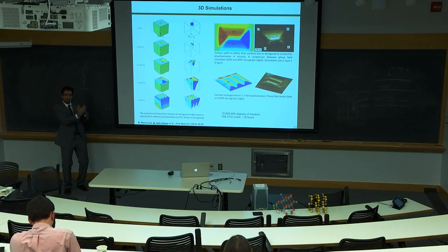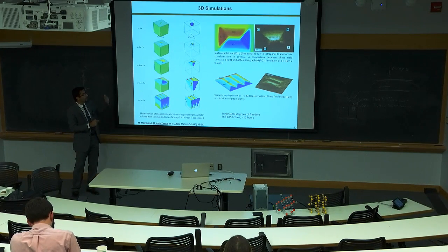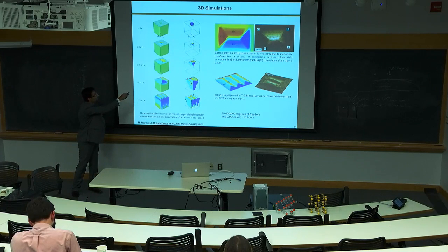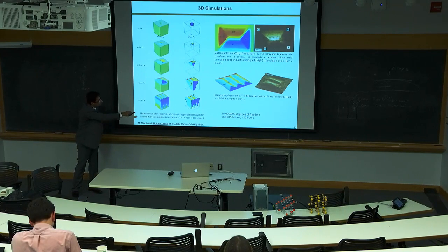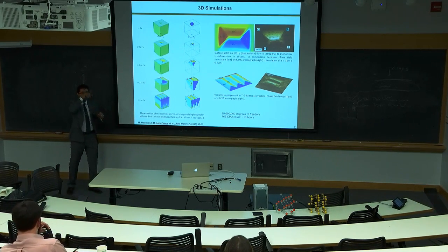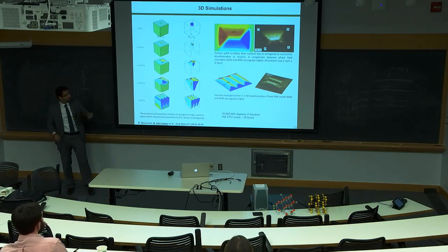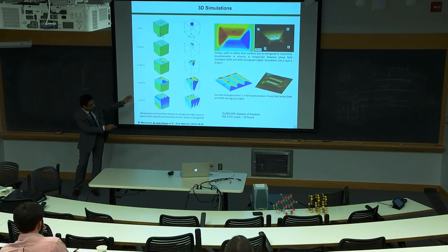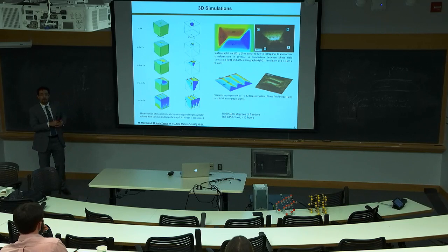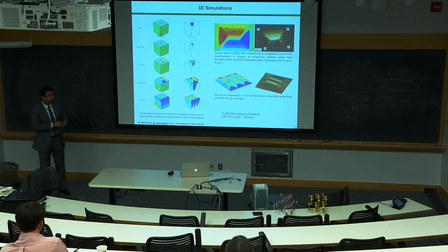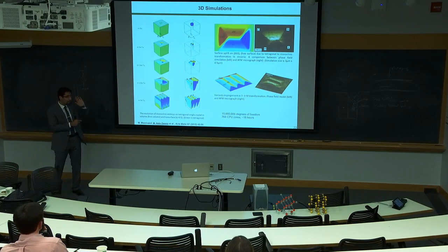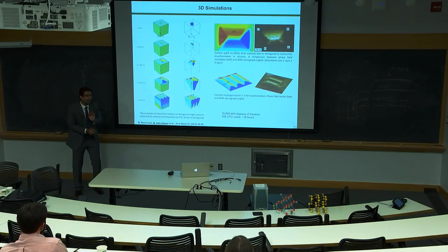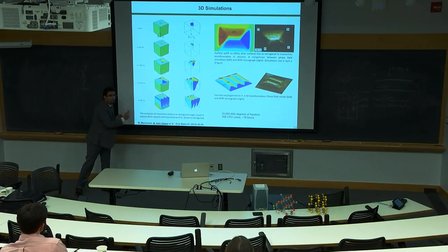It's almost a free surface. So what happens if we run it in 3D simulations and we have a free surface at the top? We get corrugations actually. These are corrugations at the surface that we predicted, and these are validations from AFM micrograph, atomic force microscopy. So we can actually quantitatively predict where the cracks are going to happen. Cracks are going to happen here. Okay.